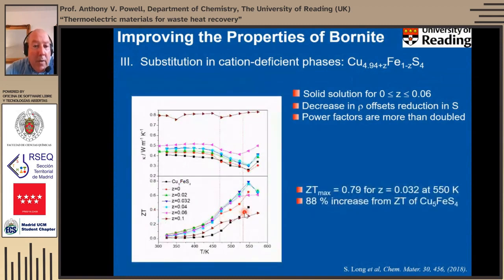And then we look at the thermal conductivity. We find that it does increase, but we're not impacting on the thermal conductivity quite as much as we were in those other series. And I think that's probably because of the vacancies. And we reach a ZT maximum that's almost 0.8, 0.79, at a very low temperature of 550 Kelvin. So this is actually one of the best performing materials in this industrial waste heat region.